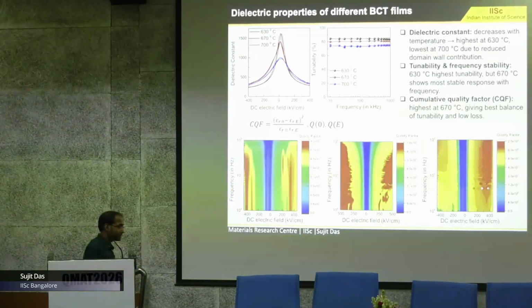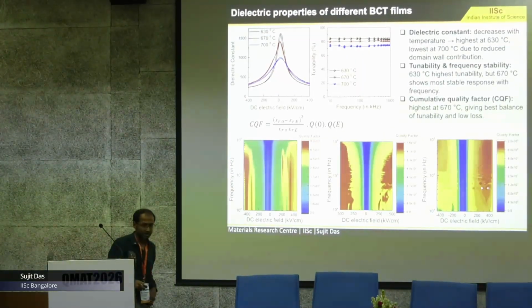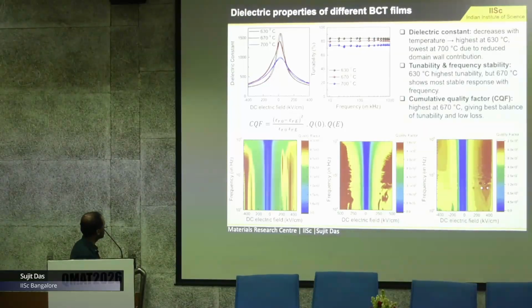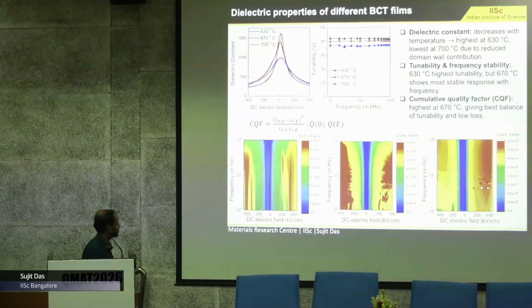And now we make the device. If we look first at the dielectric constant and dielectric tunability, we found the 630 showing the high dielectric constant with respect to the other growth temperatures. And once we look at the tunability, we found around 85 to 87% tunability for the BCT grown at 630 degrees C, and reducing for the films grown at other temperatures.